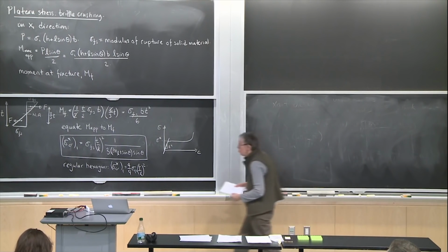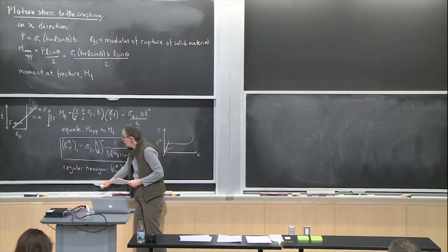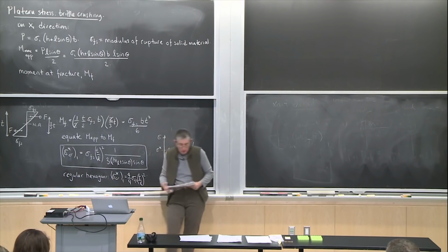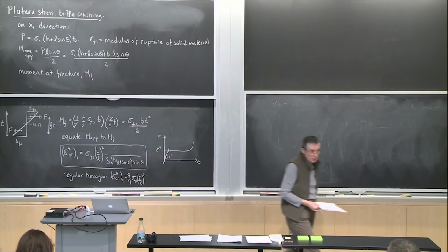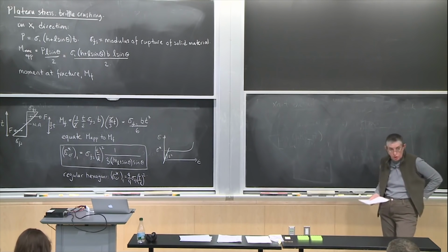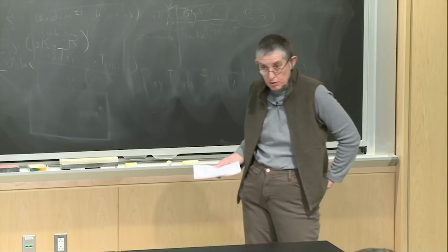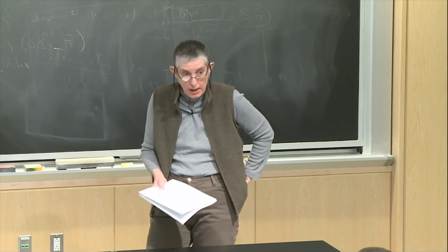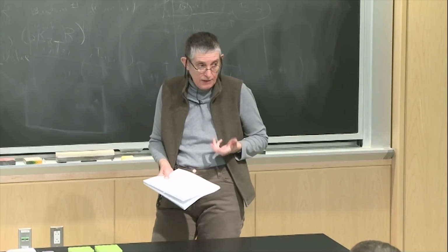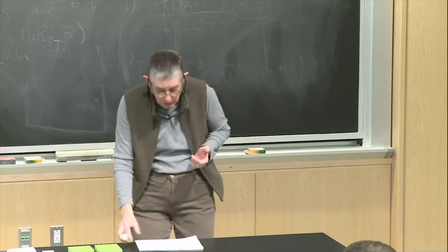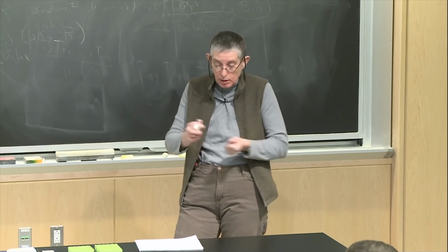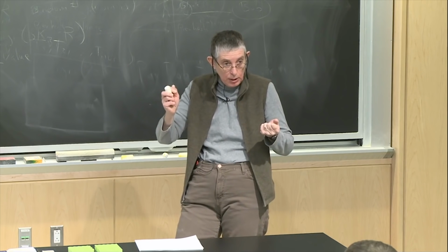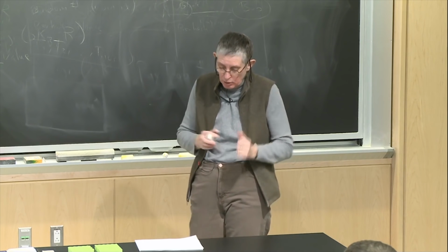And the next thing I wanted to talk about is tension. If we think about the tensile behavior, the elastic moduli are going to be just the same. So the moduli are the same in tension and compression. And then if we think about the stress plateau, we don't really have a stress plateau for an elastomeric material because there's no elastic buckling. If you pull it in tension, you're not going to get buckling. You only get buckling if it's in compression.